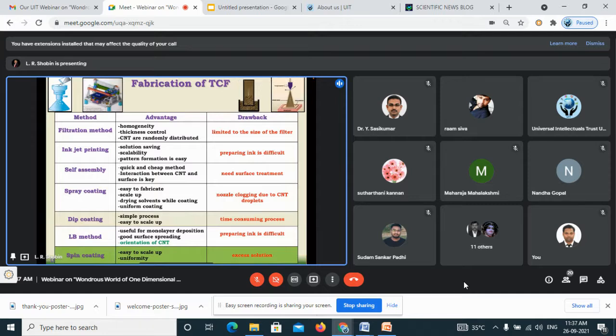Now what I have is a wire solution of silver nanowires, and I can make a dispersion also. Then the process is very simple. You spray it or spin coat it. For a small scale, you can go for spin coating. I have already mentioned the spray coating process. Here I am going with the spin coating process since it is very simple, and within a minute you can fabricate a film out of it.